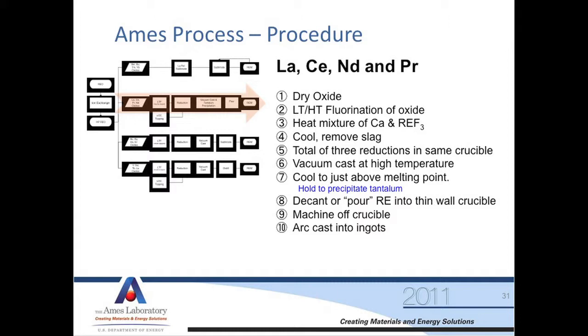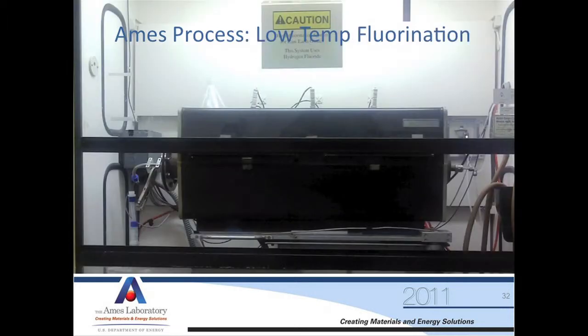And this pouring process is where we cool to just above the melting temperature, or I'm sorry, precipitation process, and we precipitate out the tantalum that may be in there. Then we decant or pour away from the precipitated tantalum. In this case, we can machine off the crucibles and we can cast into arc melt ingots.